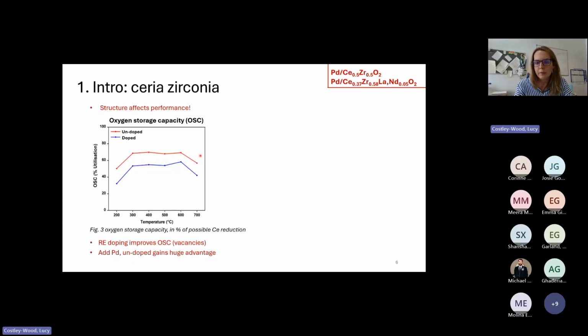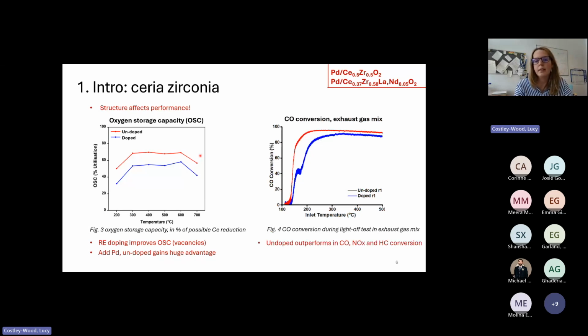Similarly, if we look at the catalyst performance by its activity, so we tested CO conversion, NOx conversion, and hydrocarbon conversion all under exhaust gas mixtures, we see again that our undoped material performs better. It has a lower light-off temperature and reaches higher maximum conversions. We also have this unusual feature for the doped material, where we have this kind of activation period that's required before the conversion can proceed.